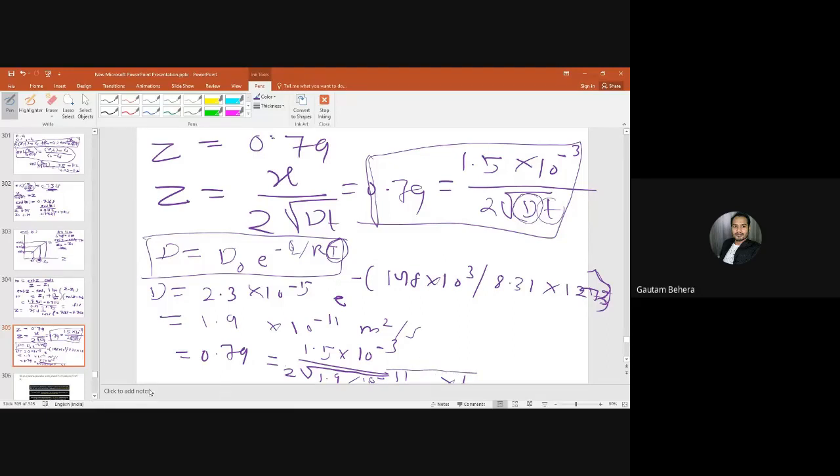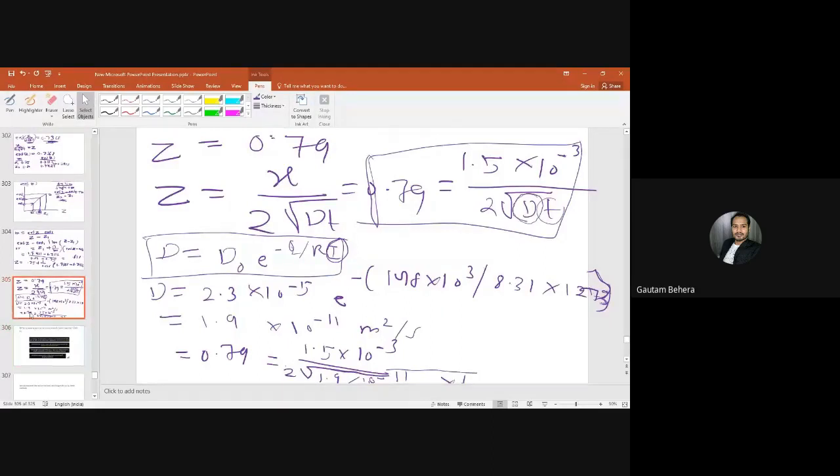So from this you can finally calculate. You have to solve this and you will get the t value in second, obviously 46503 seconds. Then you can convert this into hours if you want, otherwise that is obviously fine. So you will get nearly 13 hours.